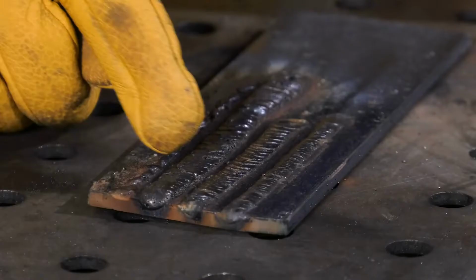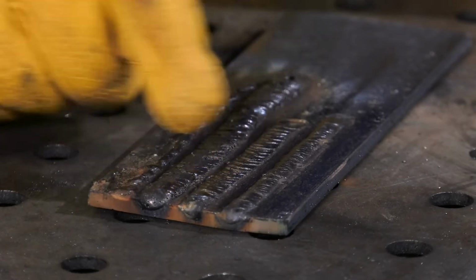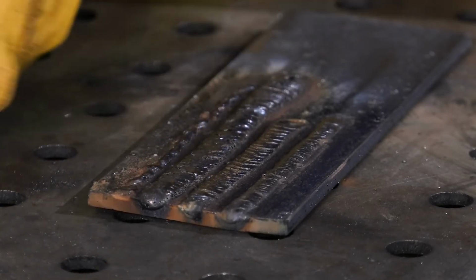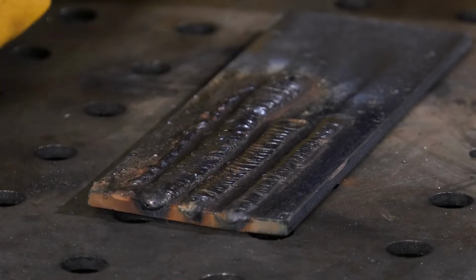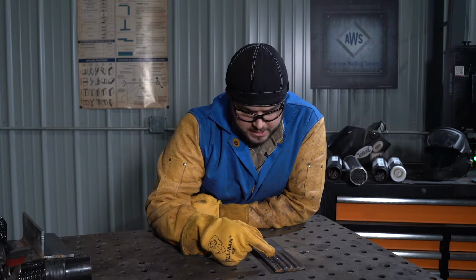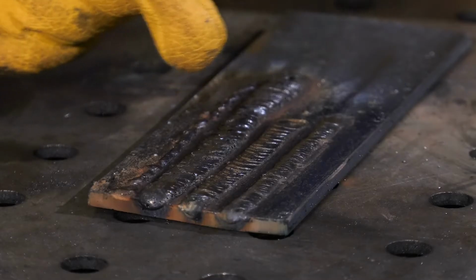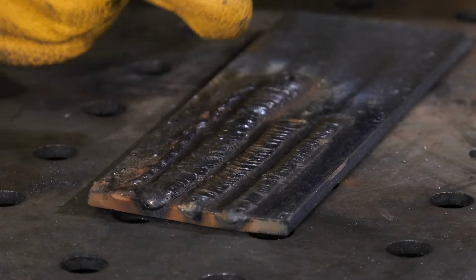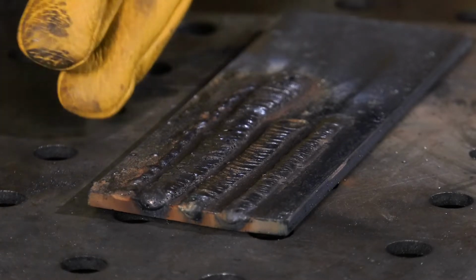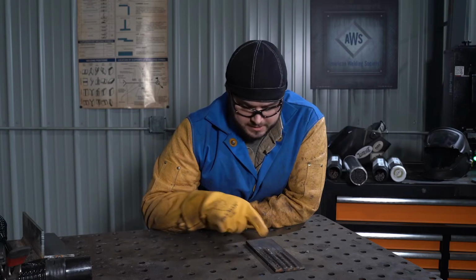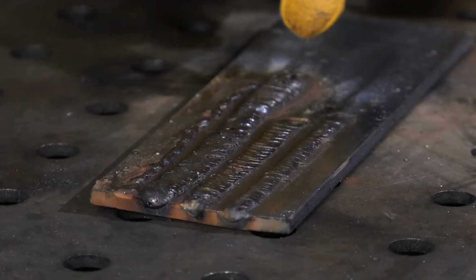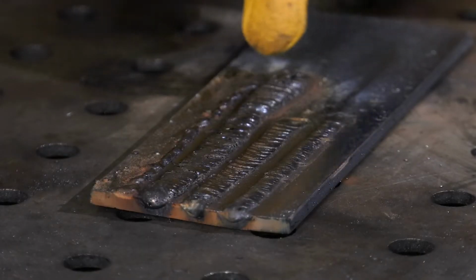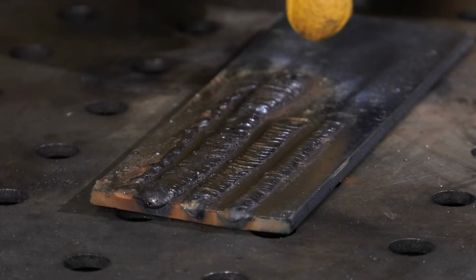Too slow. Here, we might see excess spatter along the edges. The bead will be very wide, maybe a very tall profile. We'll also see maybe inconsistencies along the toes of the weld, and the overall appearance of it will just look very big and bulky. At the end, you might see a very deep crater present, and this is also a very good indication that your travel speed's too slow.